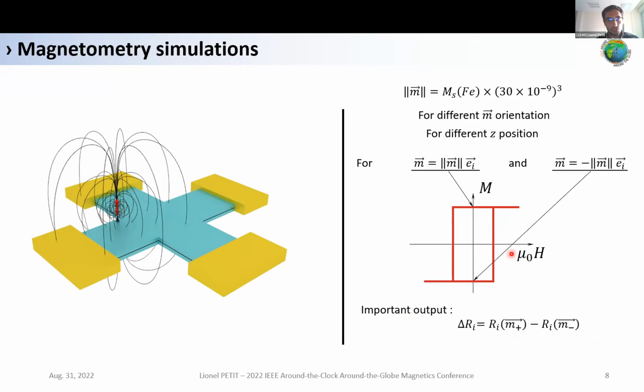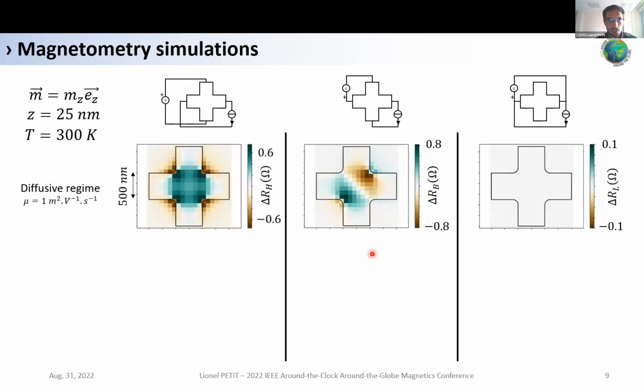And for every position, I recorded the resistances between this state and this state. It is what I will call the flip signal at remanence. And I did that for different dipole orientations and dipole positions. And here are the results for a dipole along the z-axis. In diffusive regime, we have this kind of maps.